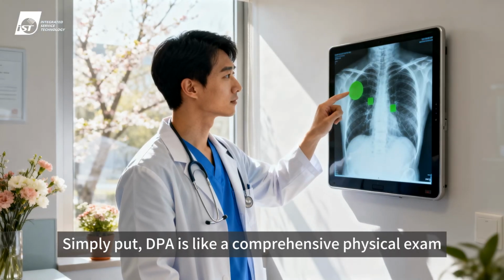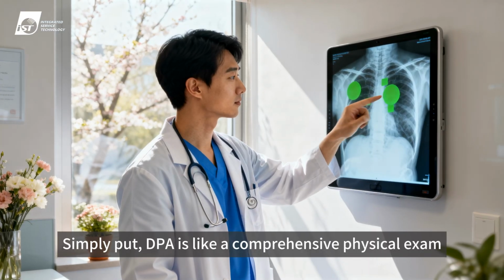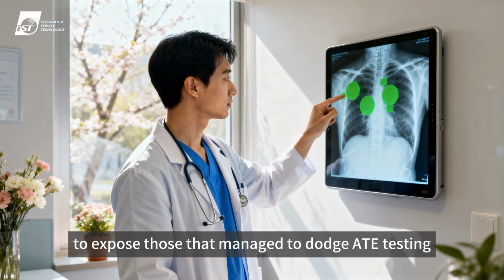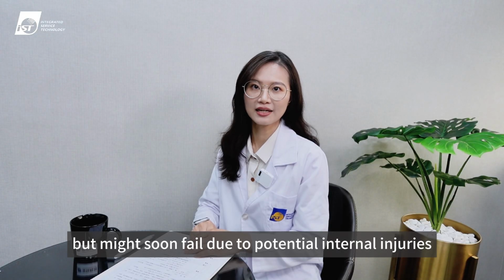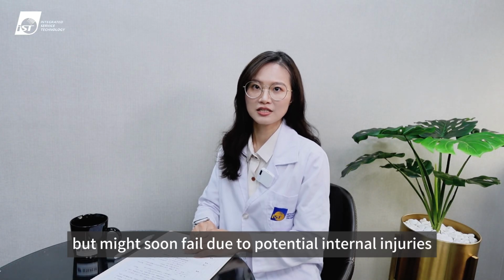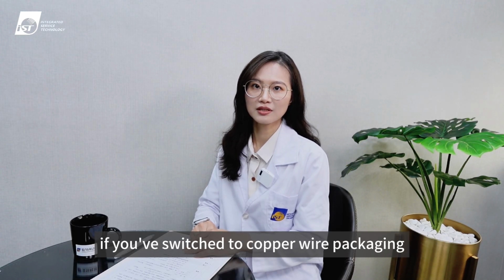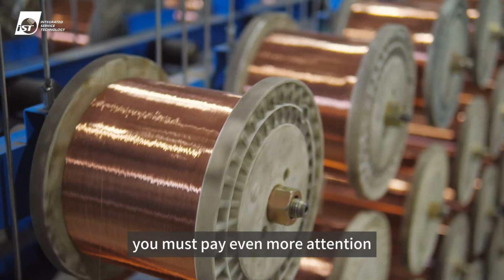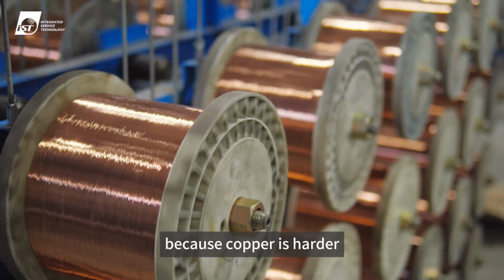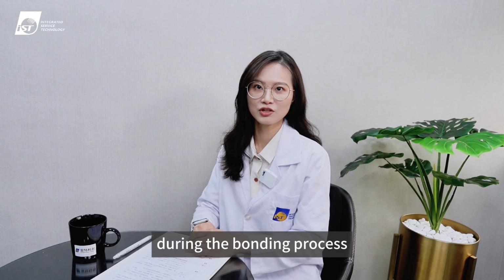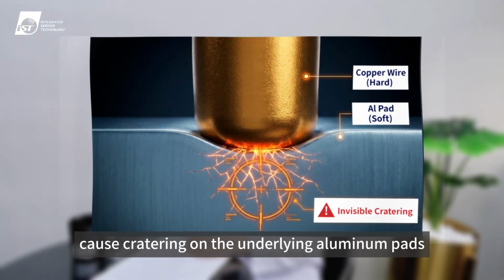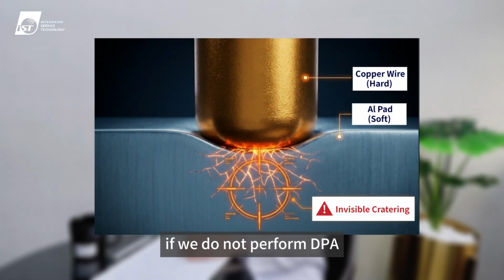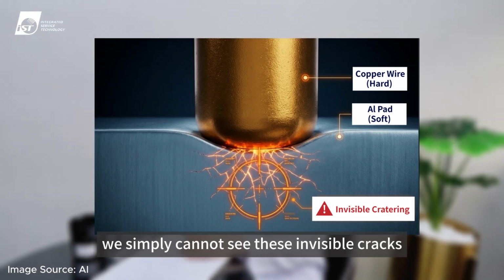Simply put, DPA is like a comprehensive physical exam. Its sole purpose is to expose those that manage to dodge ATE testing, but might soon fail due to potential internal injuries. If you've switched to copper wire packaging to cut costs, you must pay even more attention. Because copper is harder, it can easily, during the bonding process, cause cratering on the underlying aluminum pads. If we do not perform DPA, we simply cannot see these invisible cracks.